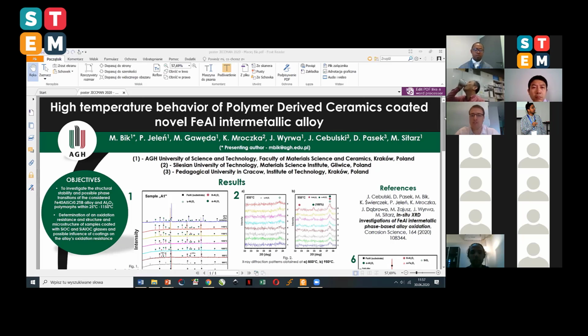So first of all, in situ XRD investigations for the pure material to investigate the structural stability and possible phase transitions of this considered alloy and alumina polymorphs within room temperature to 1150 Celsius degrees, and also to determine the oxidation resistance and microstructure of samples coated with silicon oxycarbide and silicon aluminum oxycarbide glasses, and the possible influence of coatings on this alloy's oxidation resistance.